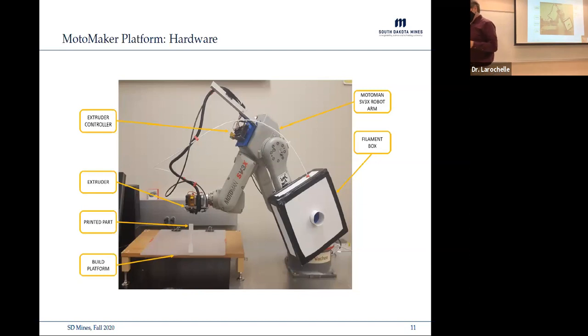What we found was that the temperature variation, and where this work was done is Florida, and the humidity variation were causing lots of issues, and not just with what we were doing, but with all kinds of 3D printing going on inside our facility. So this box helped us to control the airflow around the filament spool. It's literally just a box that keeps the airflow slowed down.